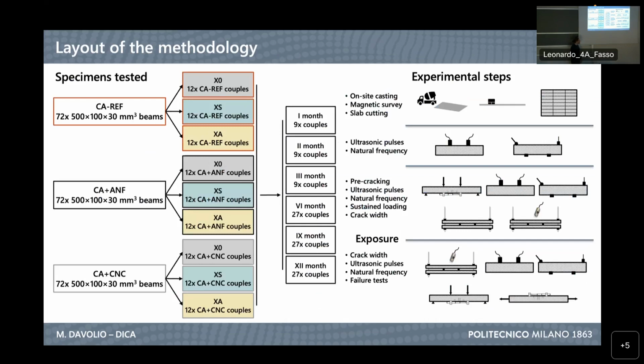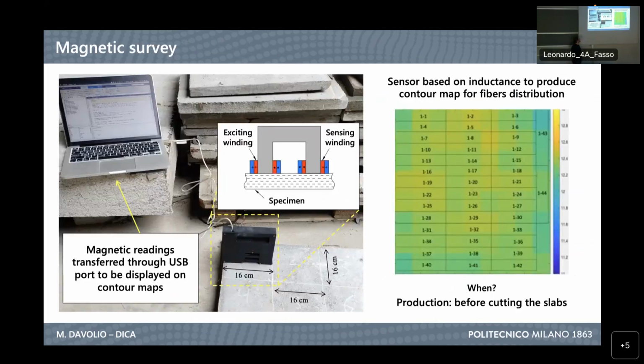After doing this, we put them inside the exposures I mentioned, and after the prescribed time, we took them out. We repeated the non-destructive measurements, namely the crack width and the two I already discussed about, and then we performed the failure test. As you can see here, I talk about couples which are nominally identical, because the idea is that for each of them, one specimen was tested under 4-point bending and the other one under direct tensile test. So now we will go through the steps I briefly described.